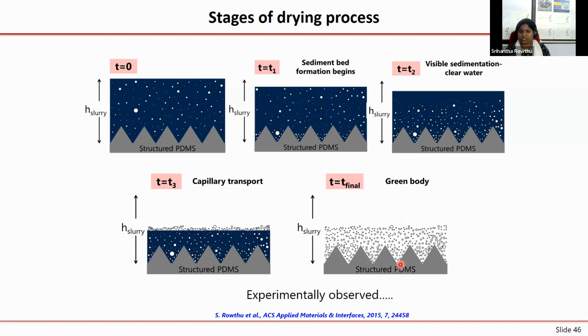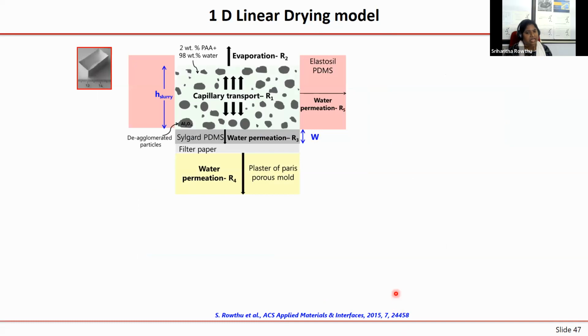So for this drying process, which contains all these transport phenomena, there is a lot of mass transport happening, right? So we can actually develop a model. I have developed a model. It's an analytical model. It's linear because the mass transport is happening in this vertical direction. So therefore, it is a one-dimensional linear drying model. That's what I had developed. If you look here, first of all, the liquid is having capillary transport in this direction. Then there is evaporation, whose rate is R2. Capillary transport has rate R1.